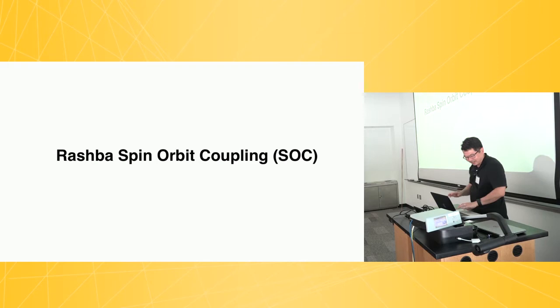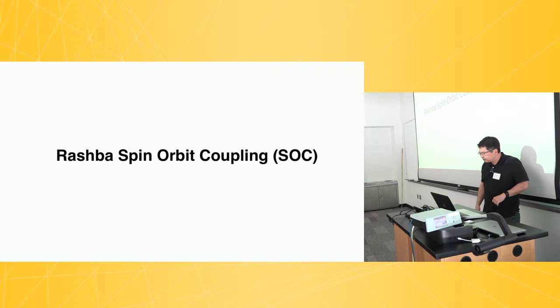I will mention that right now, the record lifetimes are like 12 nanoseconds at room temperature. And the spin diffusion lengths that people can get are on the order of 30 microns or so. In terms of these properties of any material, this is like the best at room temperature anyway. Okay, so let me pause. Any questions from students? This is the basics of spin transport and lifetime measurement.